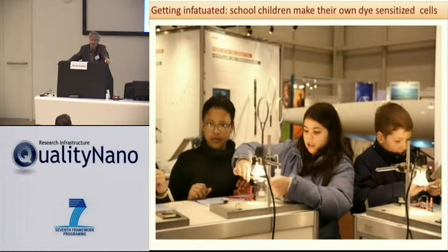It's a good point. You can also suppress the UV effect of TiO2 by doping it. That's what people do that use paints on walls. They have the same problem. TiO2 is used as a paint, so the polymer would be degraded by the light excitation. So they use some ion doping that accelerates the electron-hole recombination.